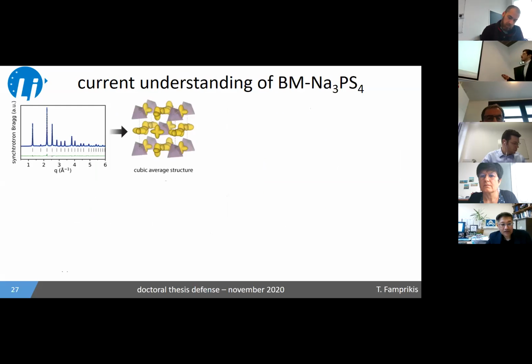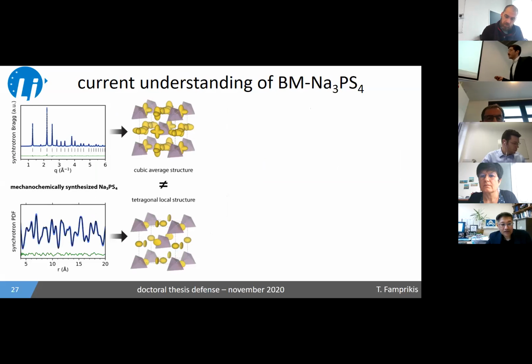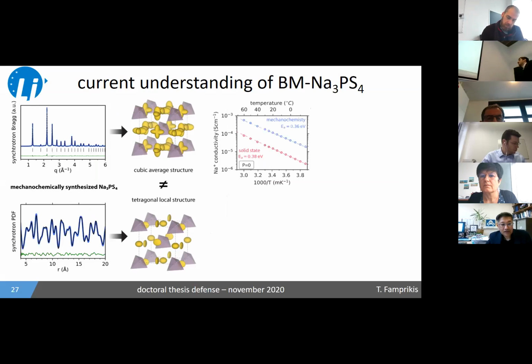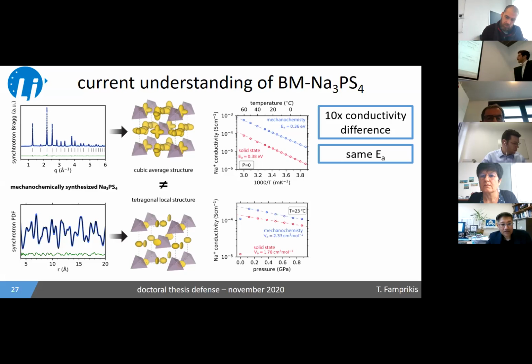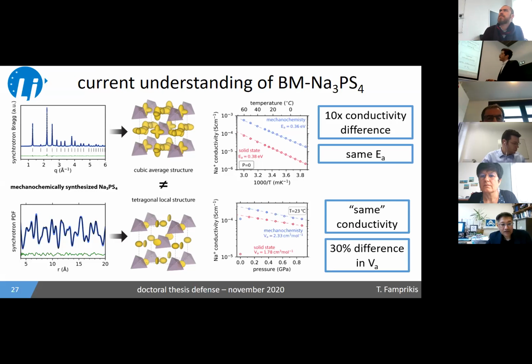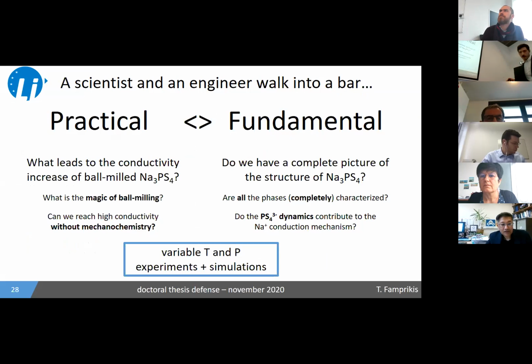So just to summarize our current understanding of the ball milling material, to finish with this part, basically Bragg diffraction tells us we have a cubic average structure, which is different from what the pair distribution function tells us, that we have a tetragonal local structure, Raman as well. When we measure the conductivity under temperature, we see an order of magnitude difference if we do not apply any pressure, but a similar activation energy. When we measure under pressure, we see the same conductivity as long as we apply some pressure, but a big difference in activation volume. So with that, I will finish on the ball milling, and I would like to go on to